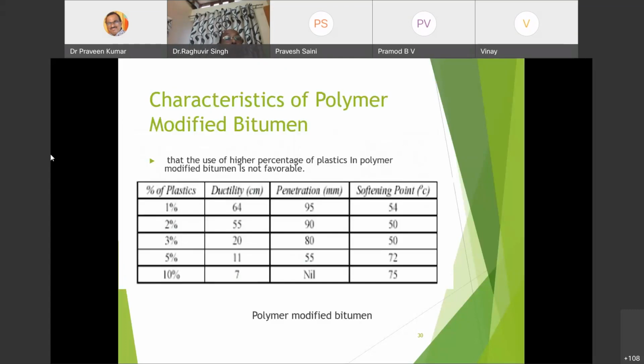These are the characteristics of the polymer modified bitumen used on our relevant project road, the PMGSY road in Madhya Pradesh state near Bhopal. PMB 40 was used, and these were the properties of the polymer modified bitumen. It means that the use of a higher percentage of plastic in the polymer modified product is not favorable. A practical study was done with plastic percentages of 1%, 2%, 3%, 5% and 10%. The results on ductility, penetration and softening point are available here.